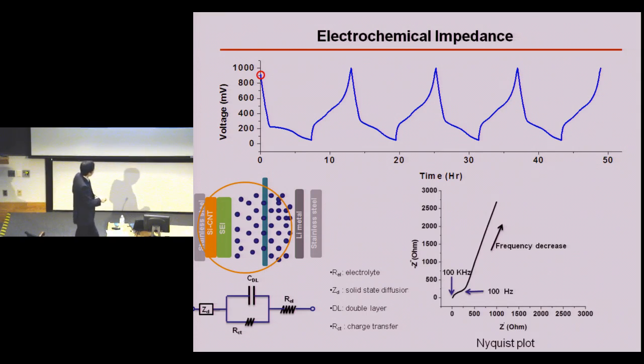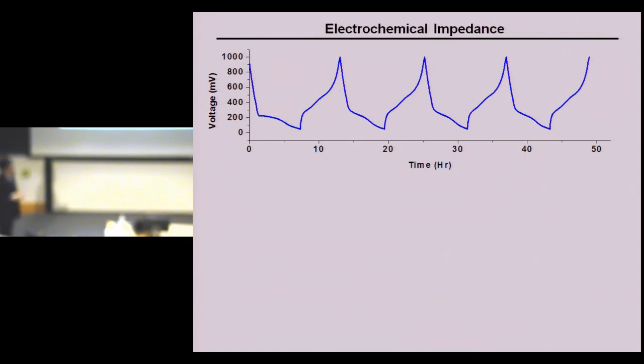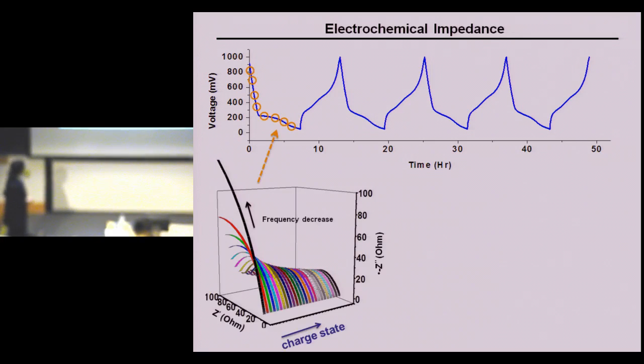So this is the impedance plot at the different frequencies. This number will correspond to the transport related to the electrolyte part. And the semicircle is actually associated with the charge transfer. So I will show you this kind of measurement at different charging states as well as different discharge stages. So this is the measurement as we charge the battery at a different state.